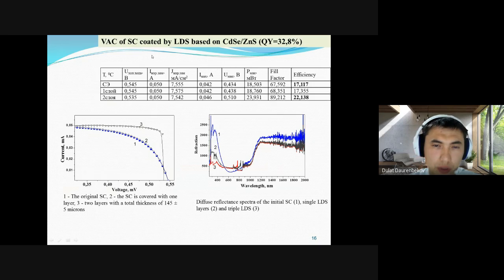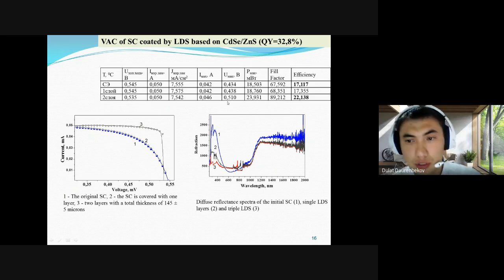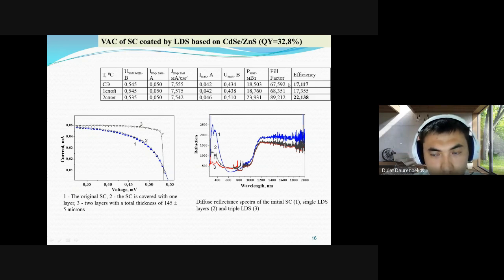Okay, here's what we measure. How we measure efficiency: as I said previously, we have a solar simulator which simulates the spectra of solar radiation on the surface of Earth, and we measured solar cells without coating. It shows 17% efficiency, and when we put the first layer, about 150 micrometers, we can see some increase in the efficiency, but not enough. And when we put the second layer, the efficiency increases to 22%. I didn't add the others because I didn't add all information, but I can say that if we put a third layer, there's a decrease in the efficiency. Maybe if you ask me, I can say why.